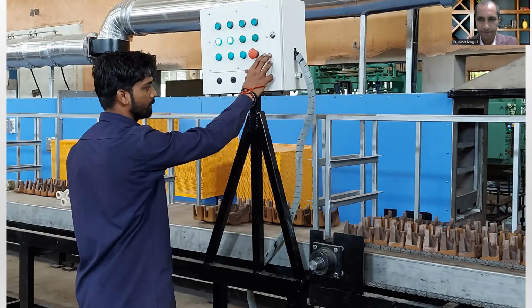Okay. And is there any particular recommendation for keeping the viscosity of the paint, or what should be the paint thickness for better result? There is a range of viscosity that people can use, but there is no issue whether you use lesser Baumé or higher Baumé. It depends solely on what kind of finish the customer wants and how much coating thickness they want to build. It doesn't impact the function of the oven. Only thing is, if you use very thin paint, then the water absorption by the core will be very high.